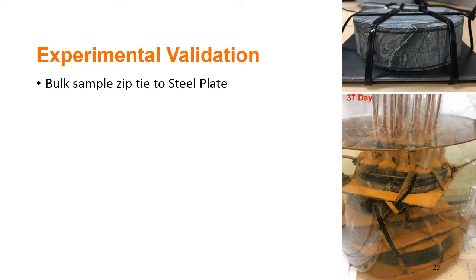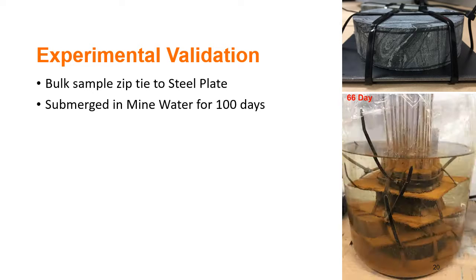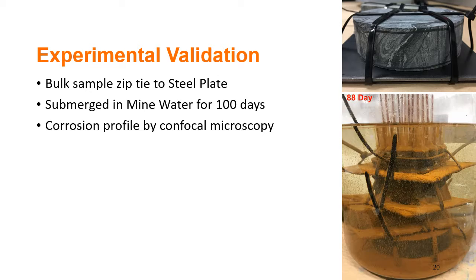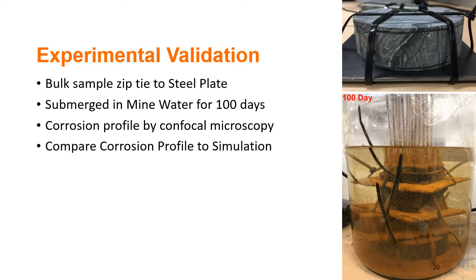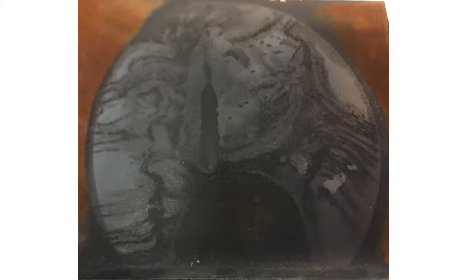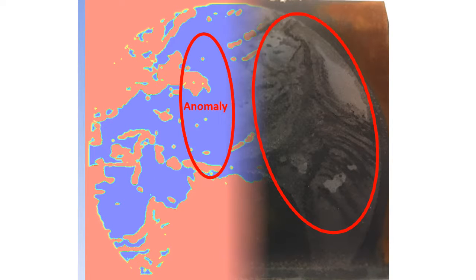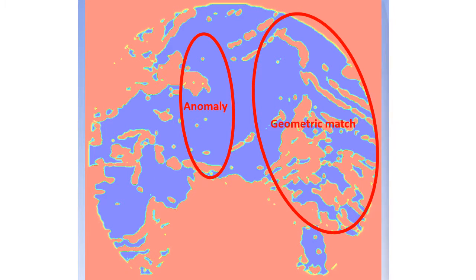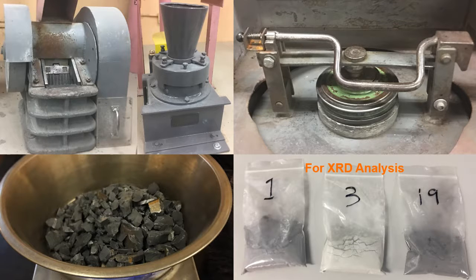Here you see the validation experiment, where bulk samples are zip-tied against a steel plate and submerged in mine water for 100 days. The steel plate is then examined under a confocal microscope. The submersion sample showed a matching corrosion profile with the simulation, except for an anomaly in the center where samples are held so tightly against the steel plate, mine water could not penetrate. As a final step, the bulk samples are pulverized for X-ray powder diffraction to positively identify mineral content.